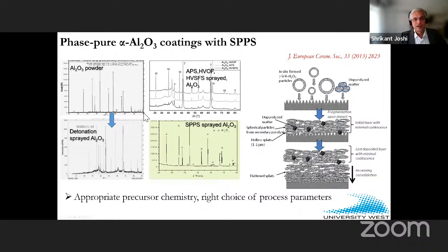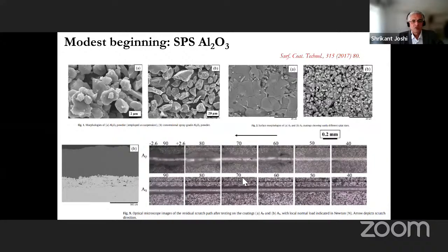You get all sorts of different phases, but not so using solution precursor, right? If you control it in a good way. So this again is old work, but there's something in there which is worthy of being exploited further by combining that, not with radial feeding as this study was carried out, but with axial feed plasma torches, which give you throughputs that are interesting. So this was our modest beginning with SPS alumina using powder sizes which are 2 to 3 microns and lower, and we got pretty good